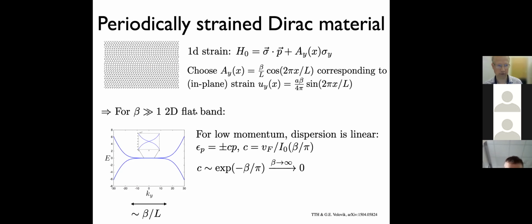If you consider beta that is large compared to 1, you actually get a 2D flat band in this system. This flat band is different from the previous one, which was p to the nth power. In this case, this remains linear. This has a linear spectrum, but in such a way that the prefactor of this linear spectrum is extremely small. So compared to the intrinsic Fermi velocity of graphene, you divide it by an exponential function. So if beta is just somewhat larger than pi, this speed becomes extremely small, and then you get an asymptotic flat band in this system.